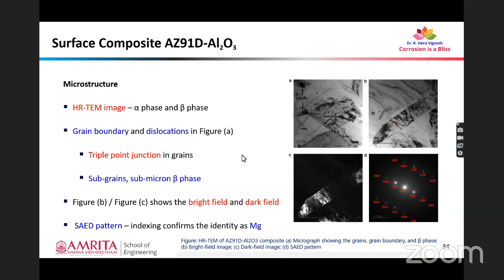To observe the dislocations, high resolution transmission electron microscopy, HRTEM, images of the fabricated composite are shown over here. We can see the bright regions are the alpha phase and the dark regions over here are the beta phase. We have confirmed this through SAED pattern analysis. We can see the grain boundary and the dislocations present in the material, and we can see the triple point junction in the grains. We can see the subgrains and submicron beta phase particles. So we have confirmed the presence of magnesium and the second phase particles, that is beta Mg17Al12, through the SAED pattern. The SAED pattern is given as figure D over here. Indexing of that SAED pattern will confirm the material for us.